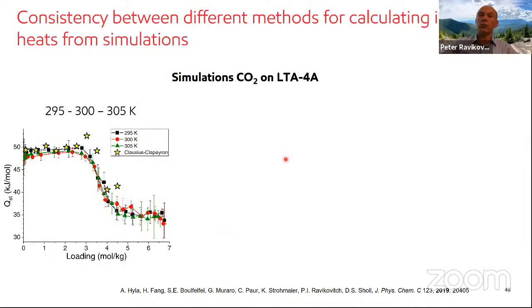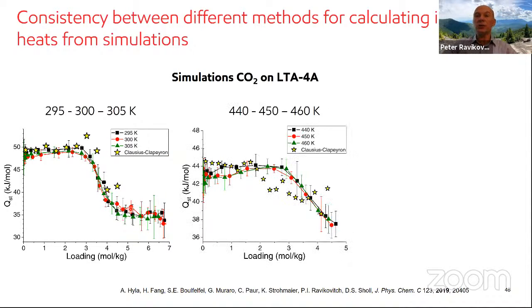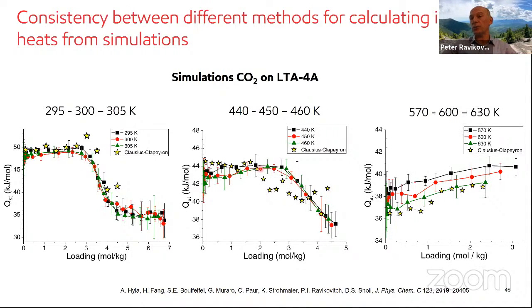We did simulations in a closer range of temperatures and used Clapeyron-Clausius to confirm the results from the fluctuation formula. As you can see, there is some scatter because molecular simulations have some scatter. So if you try to differentiate isotherms using Clapeyron-Clausius, you're going to get some scatter. But in general, there is a nice confirmation of the results. Similarly, at a higher temperature and even higher temperature. Again, full consistency between the fluctuation formula and the Clapeyron-Clausius, different routes to get to the heat of adsorption.